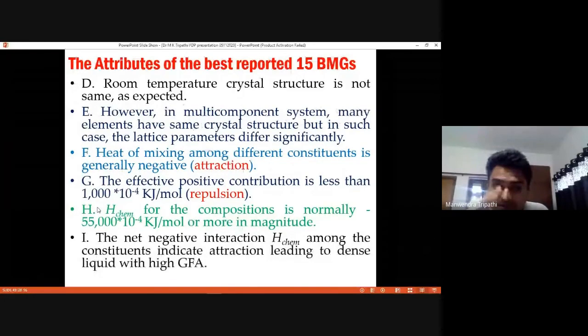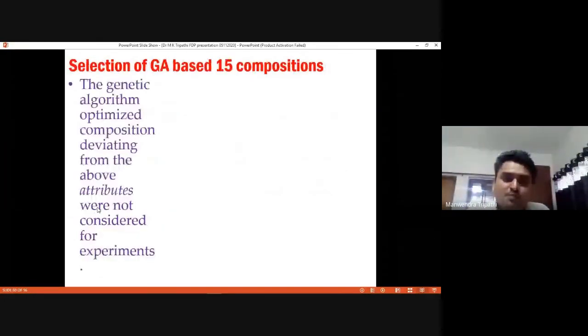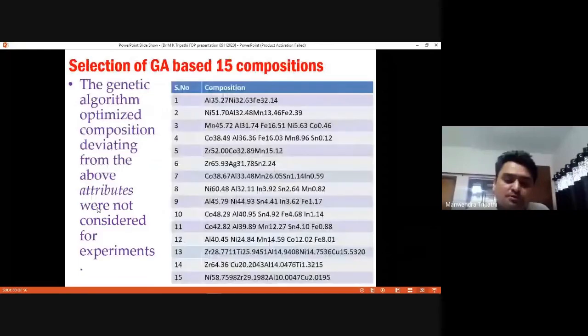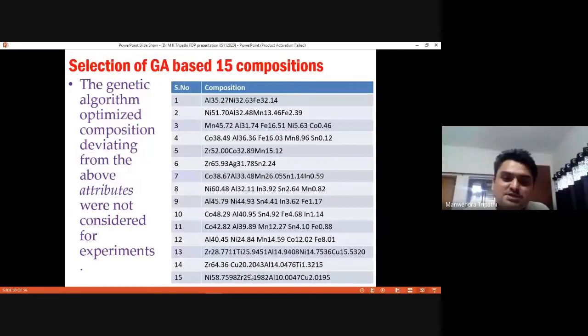But what we have done is that any genetic algorithm optimized composition deviating from the above attributes, if there is deviation, we are simply removing it, and it is not considered. After removal of those compositions, we are left with these 15 compositions, which are predicted from the genetic algorithm, right? So now it is time to go for experimental validation. Out of 15 compositions, we have further chosen 3 compositions. We don't want to increase the number, right?